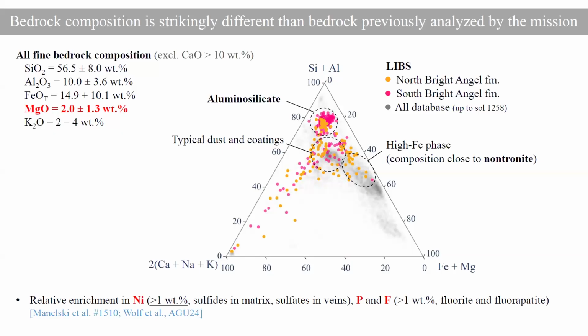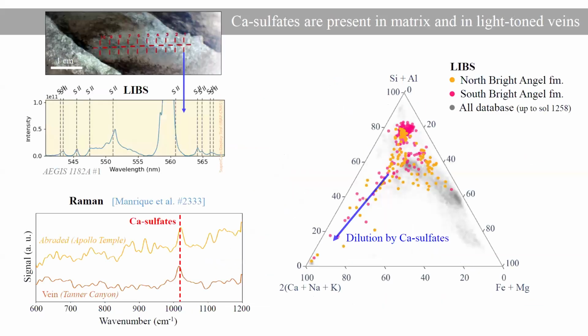Now, if we go to the next slide and come back to that scatter towards the alkali apex, here the LIBS and Raman are positive for calcium sulfates, and they are present both in the matrix as fine grains and in the light-toned veins that cross-cut the bedrock. Here we see sulfur emission lines in the LIBS measurement where calcium is enriched, and we also see some sulfate peaks in the Raman spectra.